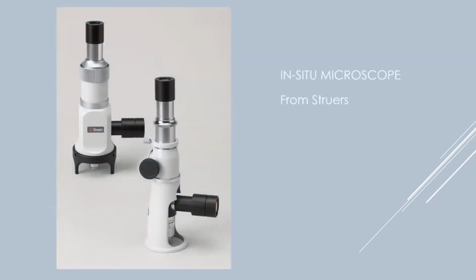In-situ microscopes are really handy, but the unfortunate thing is most of the time I'm working in locations where I can't get the microscope in the area, or I can't get my eye close enough to that microscope. So although they're useful, they just don't turn out to be that good. The other thing too is I can go up to much higher magnification if I take a cellulose acetate than using a microscope I put right on the pipe.